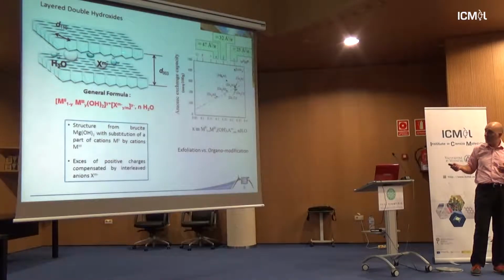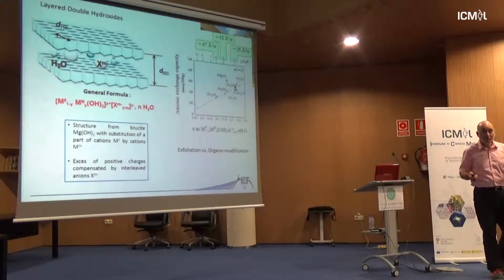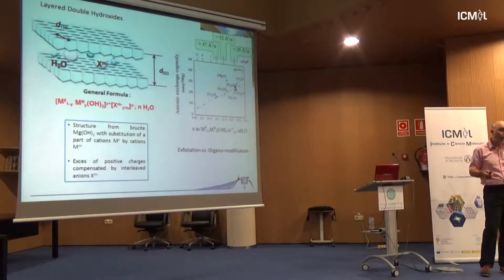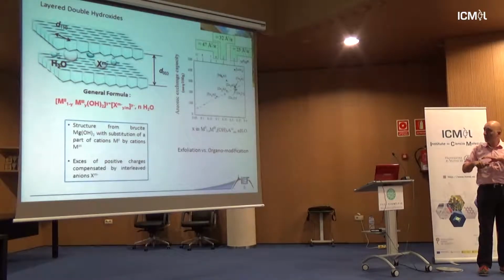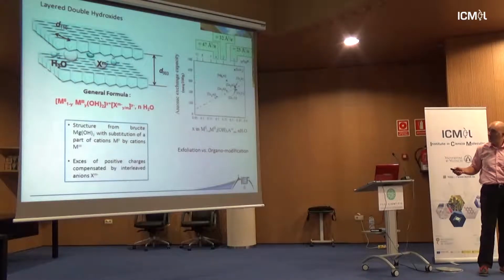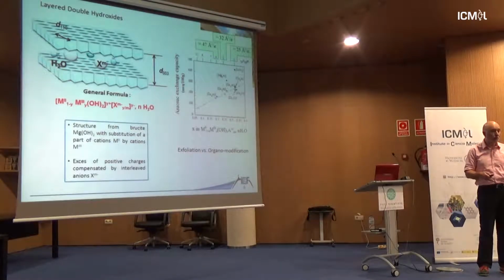And you can change the nature of the cation: zinc, magnesium, cobalt, nickel as a divalent, and for the trivalent, aluminium, iron mostly, but chromium as well, and many others. So you have a large tuning in terms of intra-layer composition, as well as the ratio between these divalent and trivalent cations. They are directly related to the loading of anion in between. So if you substitute more divalent by trivalent, you have to put in more anion, so you can load even more anion. That can be of interest if you want to do, for instance, in situ chemistry in between the layers, and you want to connect molecules, or you want to isolate them. So it's like a game. You can play with that.